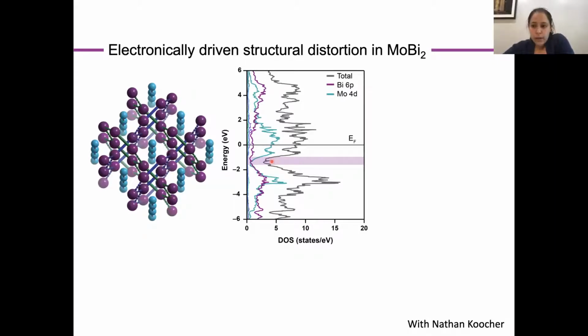In which case people are drawing on a second order Jahn-Teller-like effect in which you are stabilizing bonding states at the expense of destabilizing antibonding states that leads to this breaking of symmetry, if you would, in your structure, as well as this signature in the electronic structure as well.